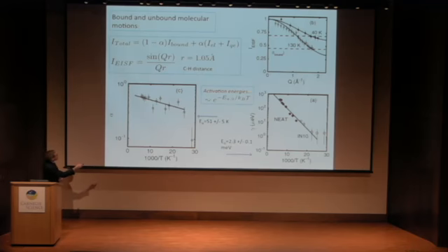So we've modeled this in terms of, first, a component that's freely rotating with this distance, which gives us this component here, and another static component that's not moving, which we've called the bound component. Based on these fits, we can calculate the fraction of the scattering associated with the bound molecules versus those that are unbound, rotating around this fixed axis with a radius of 1 angstrom. You come up with this plot here, on a log scale as a function of 1 over T. You can fit it, and you come up with a number of about 50 Kelvin. That makes sense, because the IN10 data I showed you did show dynamics onset at around 50 Kelvin. So that seems to make sense.